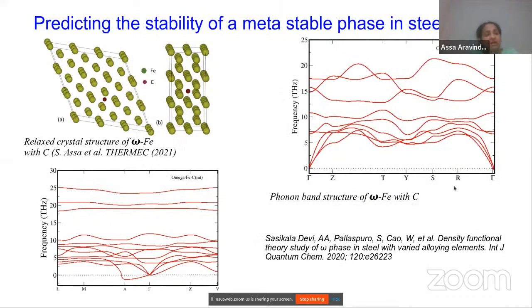Now, I will show some examples where we have successfully used DFT to calculate material properties. The slides are selected in such a way that I will give an idea of purely theoretical, purely DFT calculations, and also how DFT was successfully used to compare and collaborate with experimental results. So in this slide, in our department, we also have a steel research center. And we had an experimental result which showed that in the high resolution TEM, the experimentalist observed a new phase of a steel, which is a hexagonal phase, which is not very common. And it is produced by the presence of some grain boundaries. And we have to analyze the stability of it.